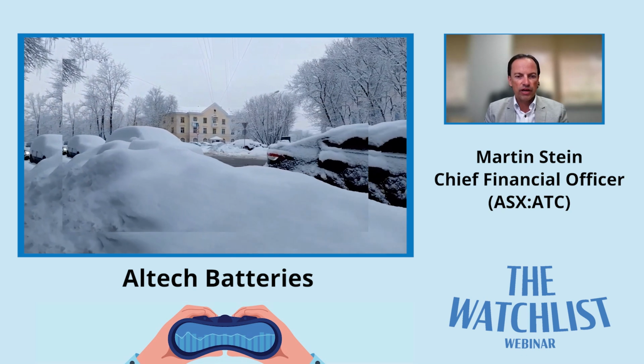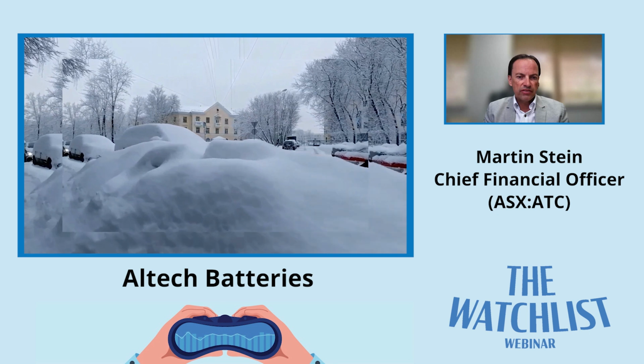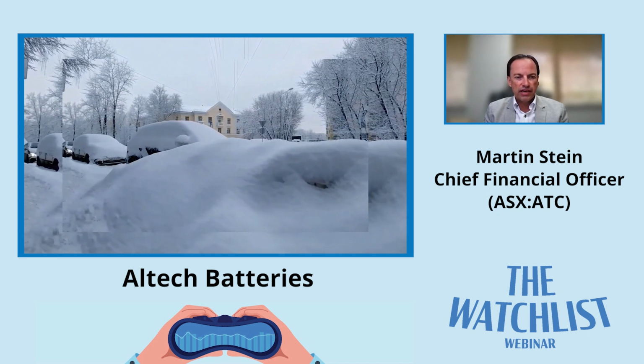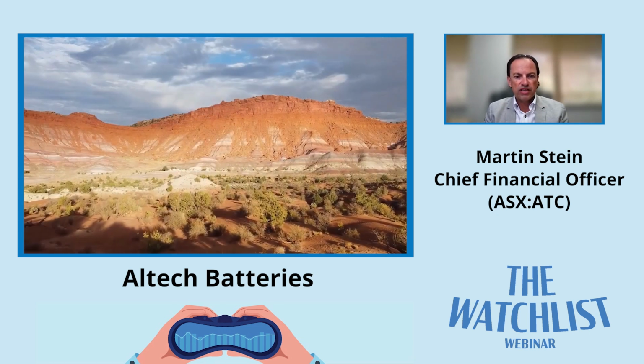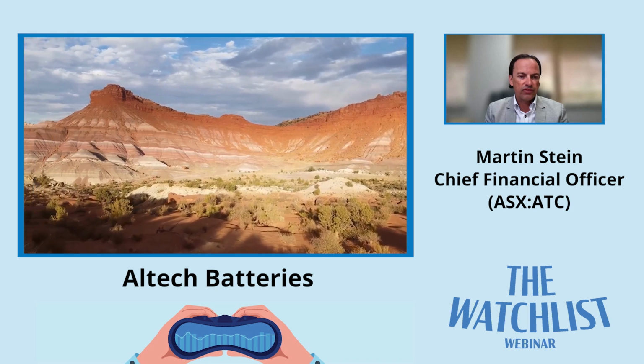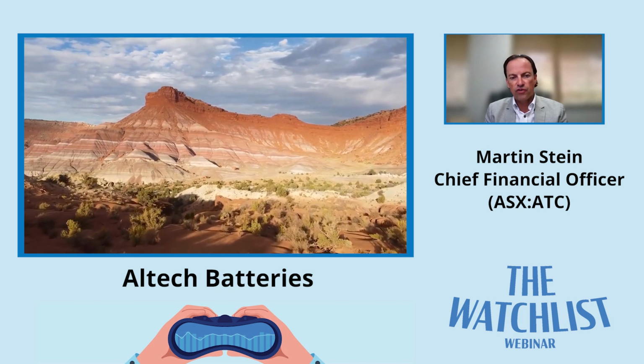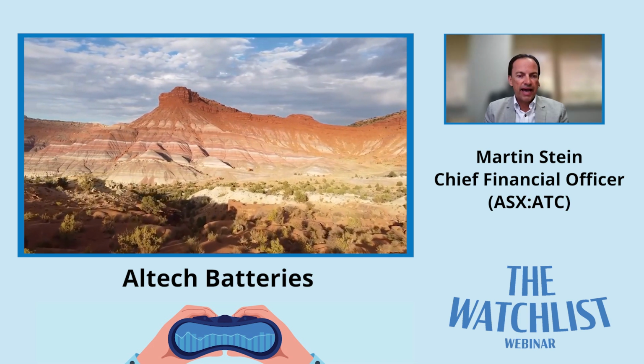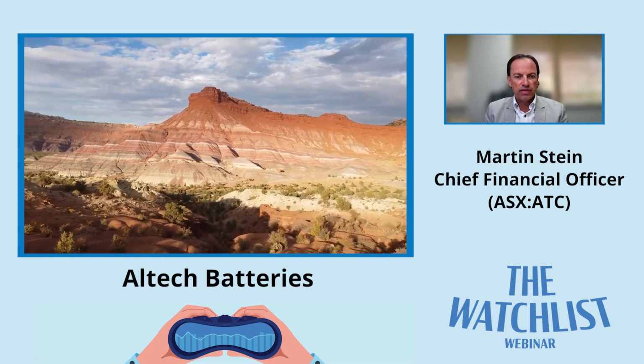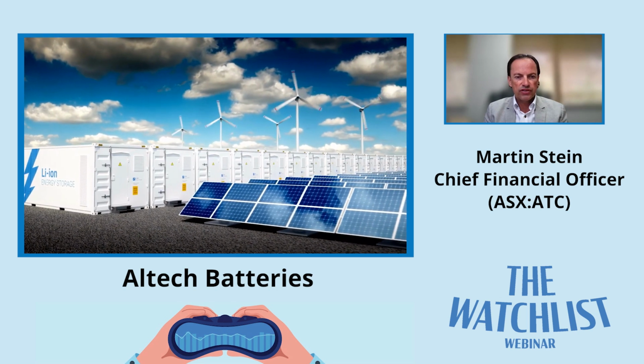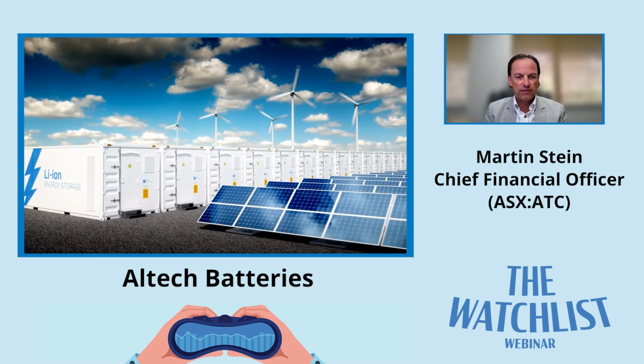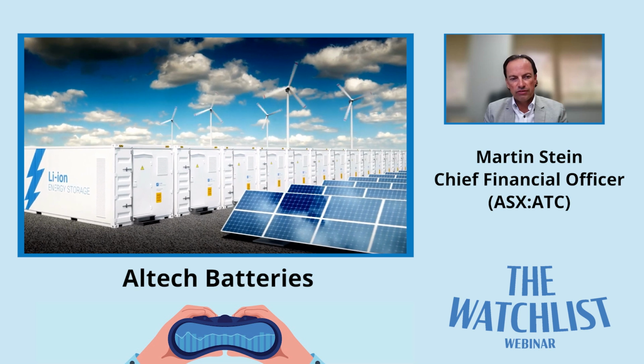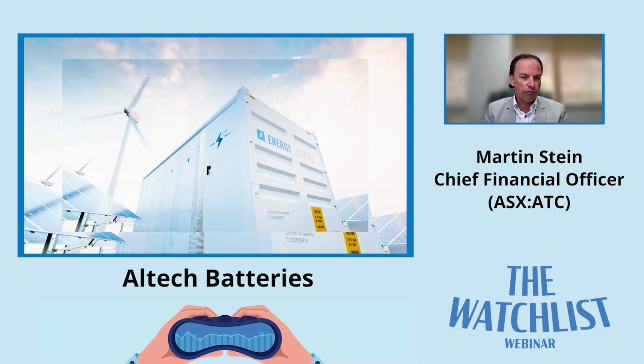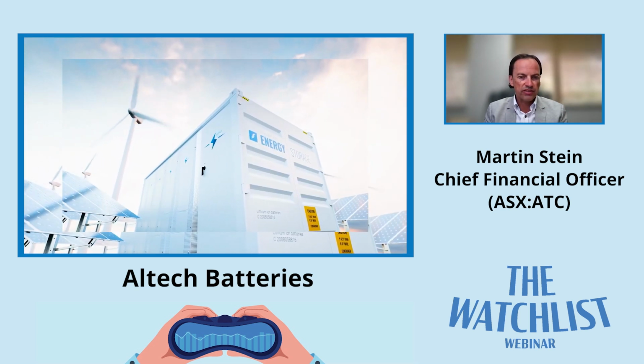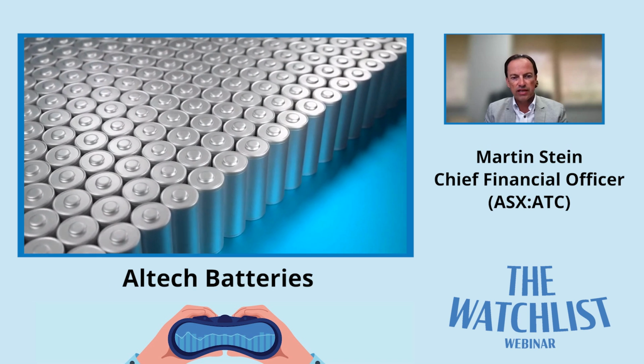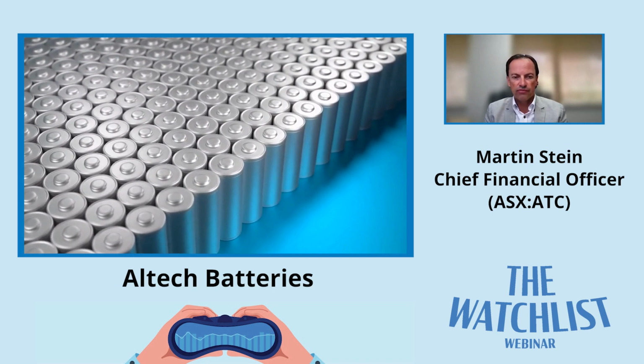the liquid electrolyte. We're also seeing that lithium-ion batteries are restricted in their temperature range. They generally operate best between 15 degrees Celsius and 35 degrees Celsius. Outside of that temperature range, the electrolyte becomes viscous and it loses efficiency and charging capacity. And we know with lithium-ion batteries, just like your mobile phones and other devices, the lithium degrades and the battery runs out quickly. So they have a limited life.